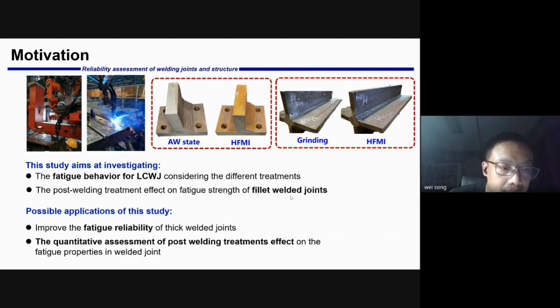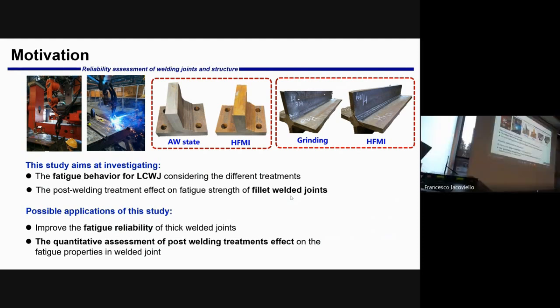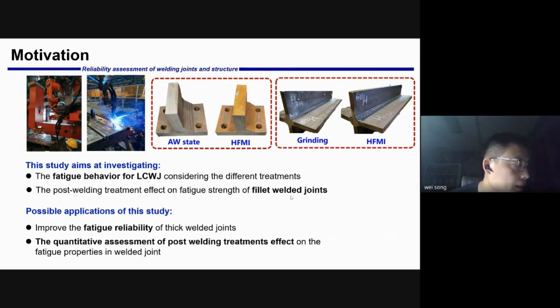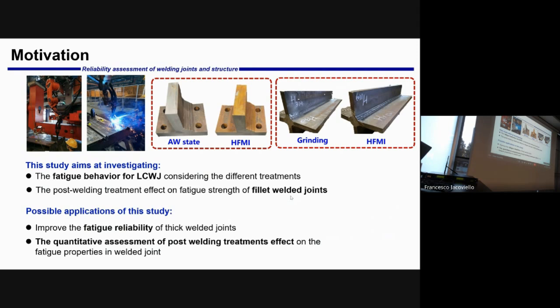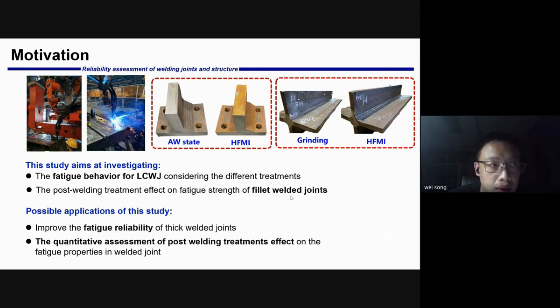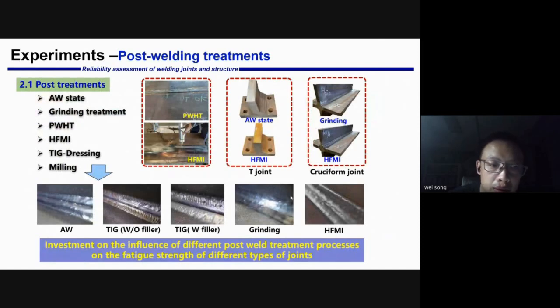The first one is improving the fatigue reliability of the thick welded joint, and the second application is to quantify the fatigue strength for different post-welding treatments for structure components. So we used five different post-treatments to investigate the fatigue property.